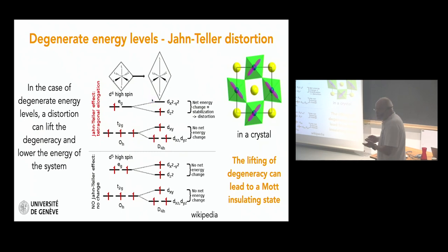Now, it's quite easy to understand what's happening. You see here that since you distorted the octahedra this way, the z orbitals are further away from the oxygen atoms, and so they go lower in energy. And this is what you see here, and the same for the xz and yz orbitals. And you see that this way the system is gaining energy. So you will go through this Jahn-Teller distortion.